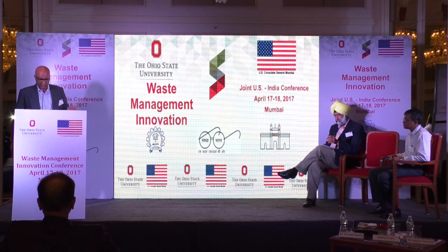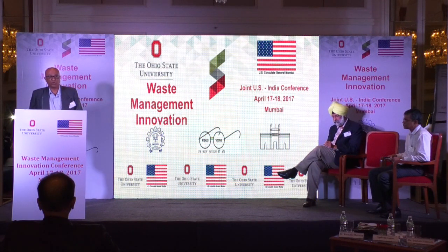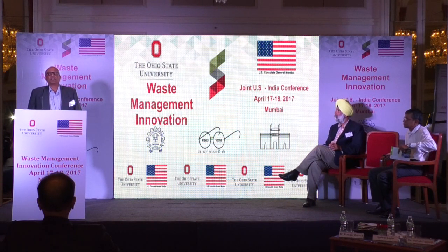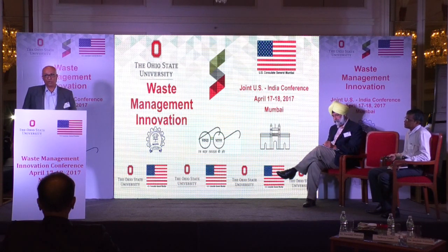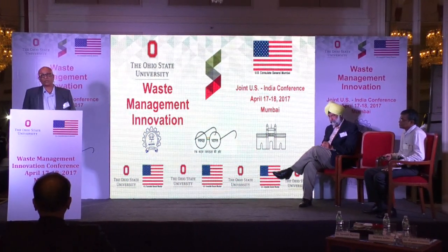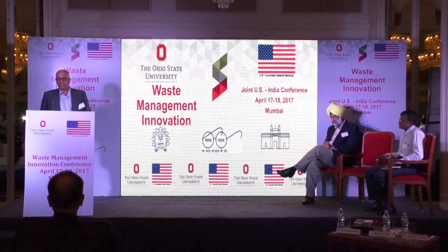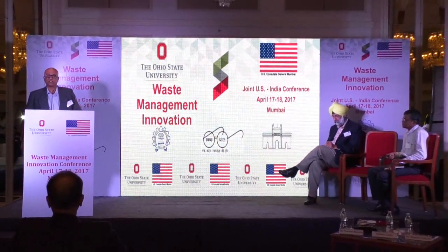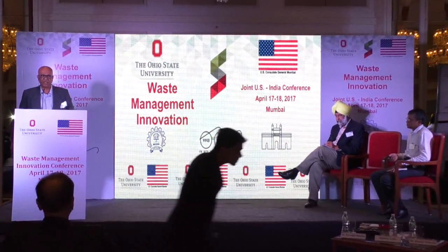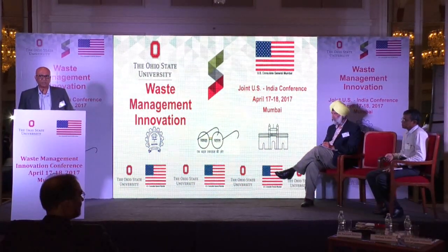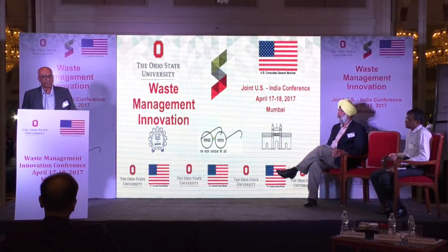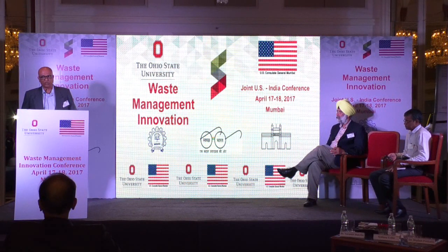One of the areas which Tarunjit didn't touch upon, and I will briefly tell you, is the operation of a power plant. Coal is burnt in the boiler, and there are two forms of ash generated. One is the fly ash, the other one is the bottom ash. About 80% is the fly ash, which is collected in electrostatic precipitators, and you have different fields wherein you can collect it in the dry mode. And 20% is the bottom ash, which remains there, really hot, and that is cooled down with water and kept in an ash pond. So we've looked at both of these, the 80% as well as the 20%. And let me talk about some of the things that we've actually done.